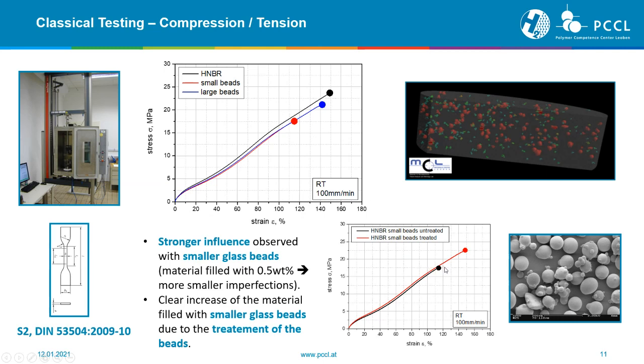And what we then finally also found, just to give you an idea and to show you the influence of this treatment, was that with the untreated material of these small glass beads, we found a lower stress and strain at break. Additionally to the tests, we've also implemented some micro CT measurements with another K1 center in Leoben, the material center. And you see here red dots the bigger glass beads and then the smaller glass beads. And we also looked directly at the glass beads, where you can see here the results for scanning electron microscopy.